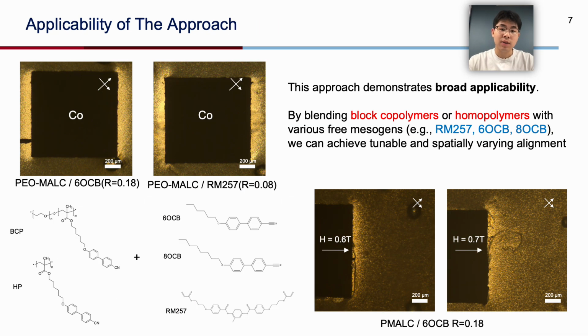We also show that this approach can be broadly applicable. We tried the block polymer mixed with 6OCB, mixed with RM257. We also tried homopolymer. They all work. And we believe as long as you find the proper molar ratio and the proper magnetic field, by blending block polymer or homopolymer with various free mesogens, this spatially varying alignment can all be achieved.